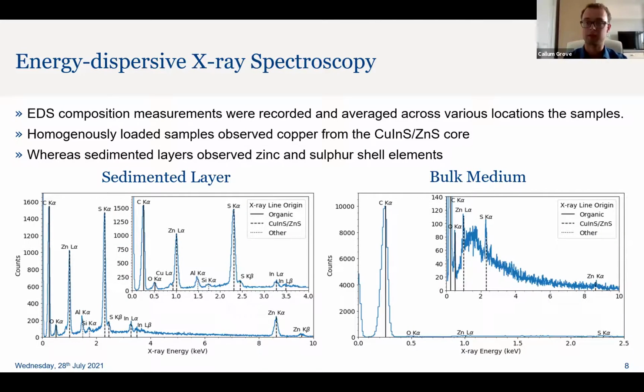So we confirmed the loading rather than just saying the quantum dots are yellow, therefore they're in there. We wanted to quantify how much the loading was. And so we did this through energy dispersive X-ray spectroscopy. These are example spectra of a sedimented layer and a bulk medium. You can see the characteristic X-ray lines from the zinc and specifically the sulfur.